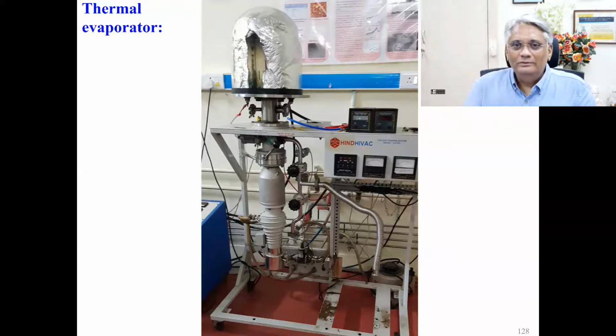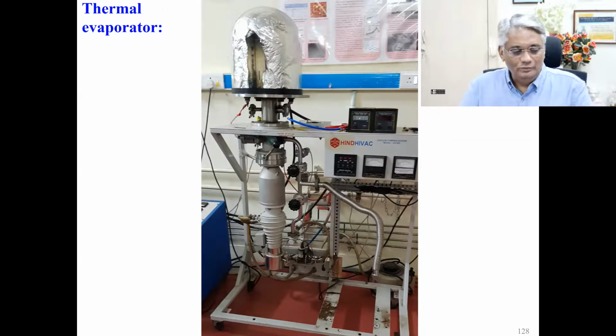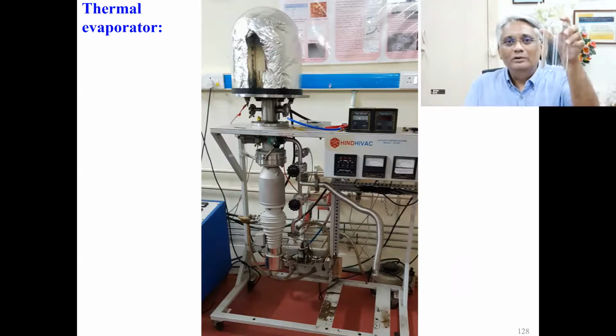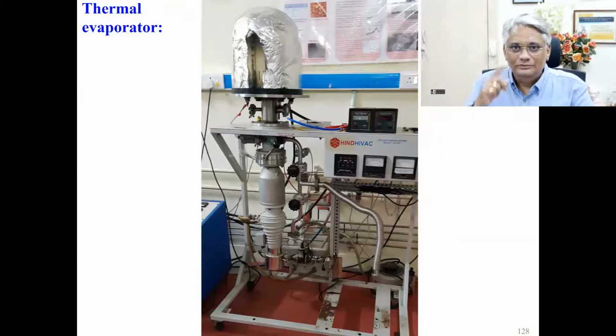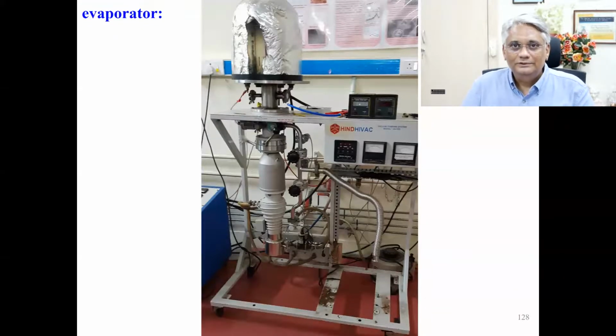But that may not be the silver film, because the silver atoms, when they move towards the substrate on which they get deposited, they also pick up oxygen from the surroundings, and so you get a nice silver oxide film, which is an insulator. So that's the reason why you need to remove all the air molecules from the chamber. So it's very important.